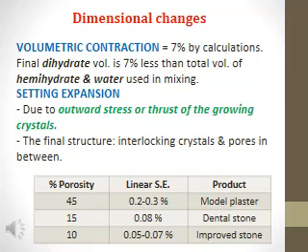Dimensional changes that occur during setting of gypsum products. Theoretically, they found by calculation that the final volume of the dihydrate is less by 7% than the total volume of the reactants, which are hemihydrate and water, used in the mixing, and therefore they suppose that the reaction is accompanied by contraction. But this is not the actual situation.